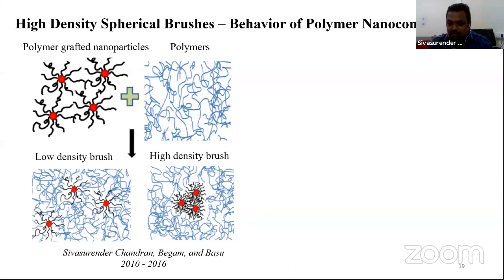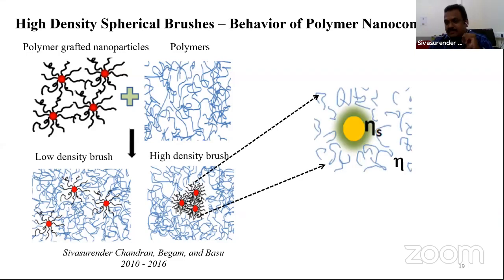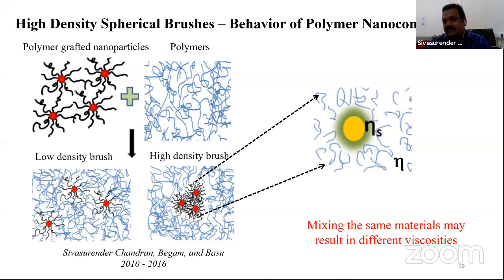And now, what is the consequence of such lower density of the polymers at such interfaces? Then you could have viscosities at the interface which are quite different from the viscosity of the surroundings, right? If you look at the interface between the particle and polymer, the viscosity there could be significantly lower, even orders of magnitude lower than the viscosity of the surrounding medium. And hence you could control mixing of materials of exactly the same nature, and their viscosities and viscoelastic properties, over orders of magnitude.